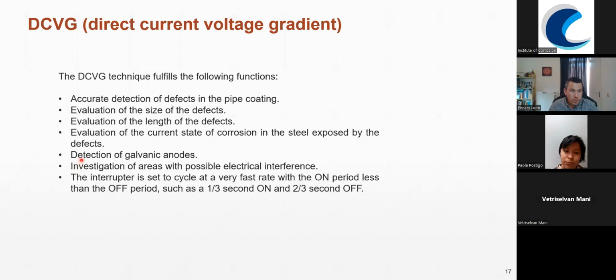We can also confirm the location of galvanic anodes, and we can investigate areas of possible electrical interference. And in this case, the setup for interrupting the TR, if we have CP, is different. We set the cycle very fast to have an on period less than the off period, meaning that it could be, for example, 1/3 of a second on and 2/3 of a second off.